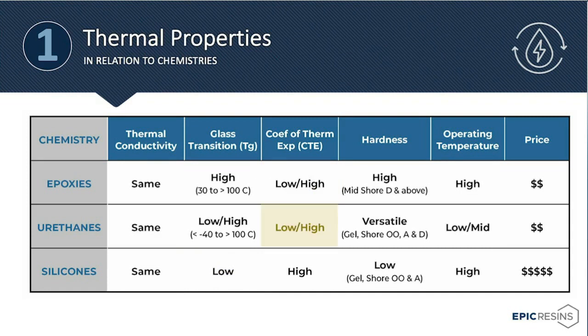Urethanes also have this ability, and that also comes from their variability of cross-link density and their variability of fillers that we can use. Silicones, because they have a low cross-link density, are generally going to have a high coefficient of thermal expansion. As we look at hardnesses, epoxies are going to have high hardness, again, due to their high cross-link density. Urethanes have some versatility.